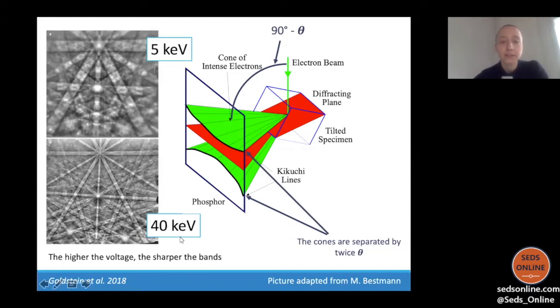So with a higher acceleration voltage, you might be able to resolve sharper Kikuchi bands, but it doesn't help us very much as sedimentologists, because this works very well with metals and it works very well for material scientists, but for the type of minerals that the sedimentologists, especially carbonate sedimentologists, tend to work with, this acceleration may be too high. So we'll be using these blurry patterns that we see on the top. At least this is what I have to do.